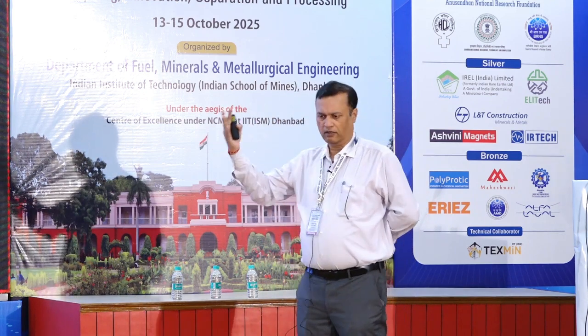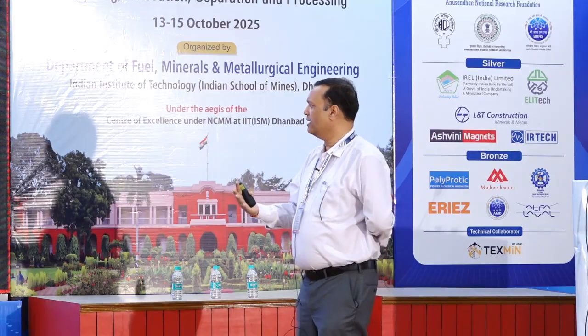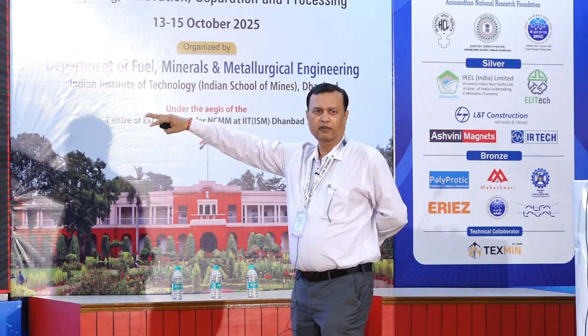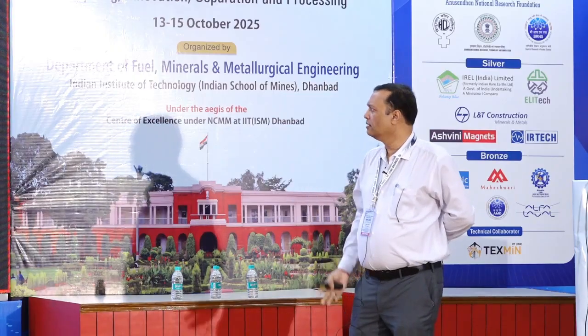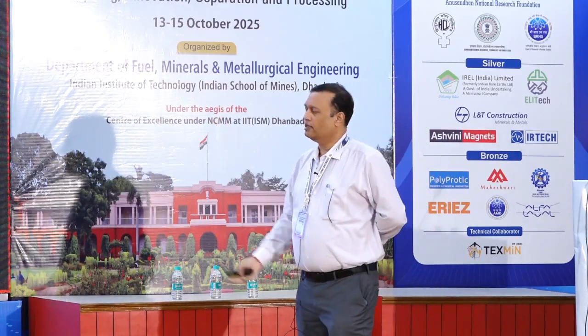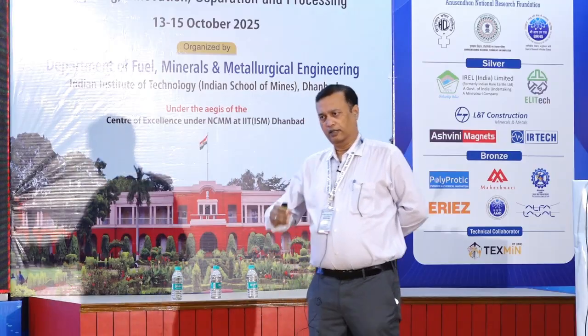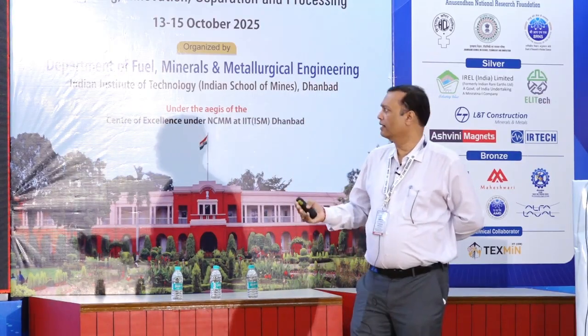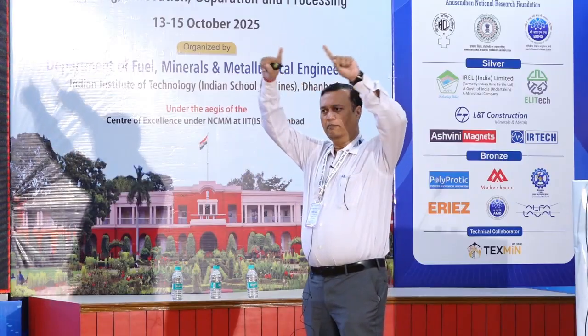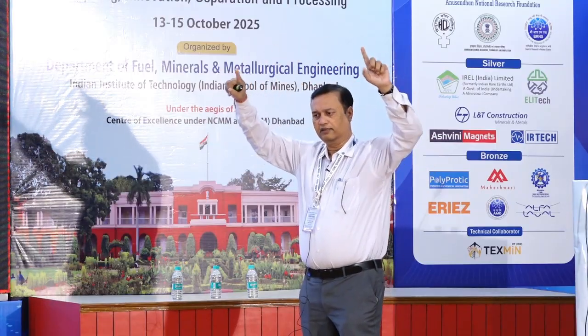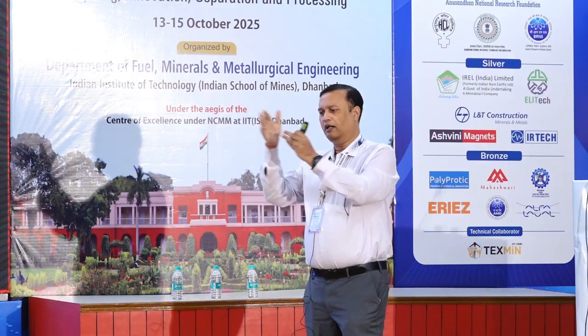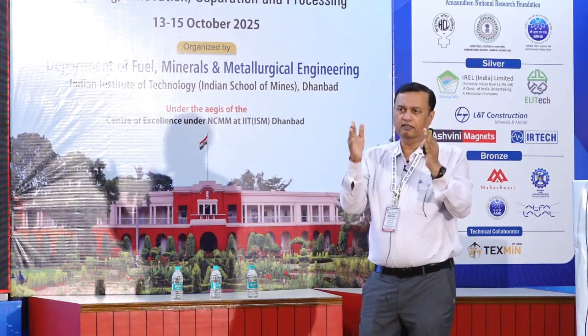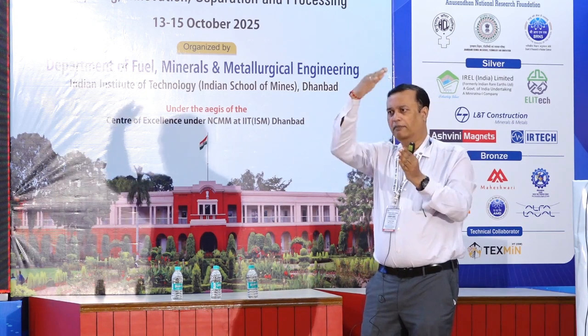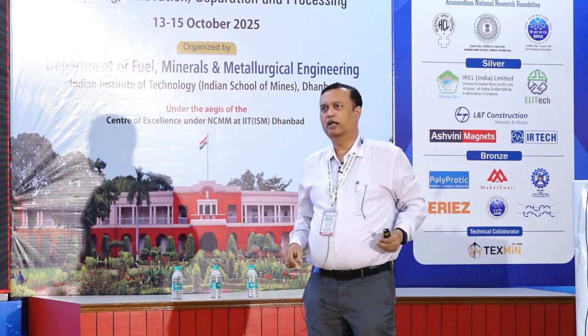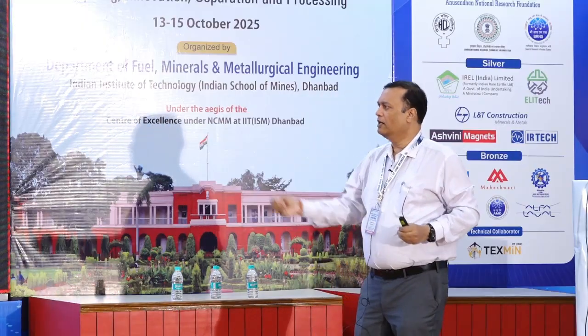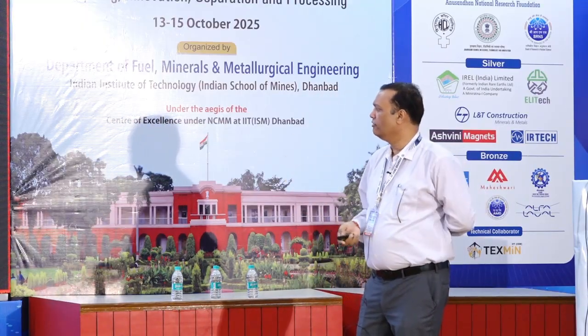The whole process technology is developed such that we can minimize these impurities in the NdFeB magnet to increase the energy product. The Nd-rich phase plays a very important role in determining the coercivity of NdFeB magnets, because it encompasses the grains, so one grain and the other grain cannot interact. That is, it breaks the magnetic coupling, and because of that you get very high coercivity. That is the requirement to get high coercivity in NdFeB magnet.